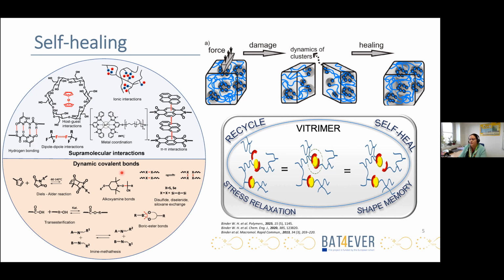On the other side, we have the possibility to introduce so-called dynamic covalent bonds. That means that this dynamic of the opening and closing of the covalent bond can be generally achieved by shifting the equilibrium from an energetically higher to an energetically lower state. The basic principle of the self-healing via these dynamic covalent bonds is the opening and closing of the bonding site, which leads at the end to the corresponding equilibrium.